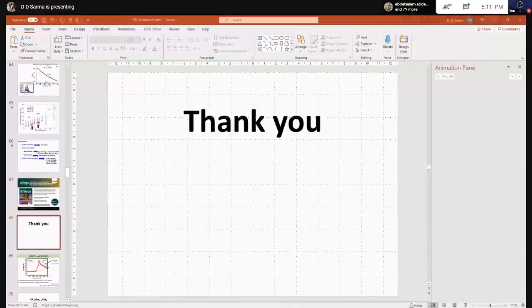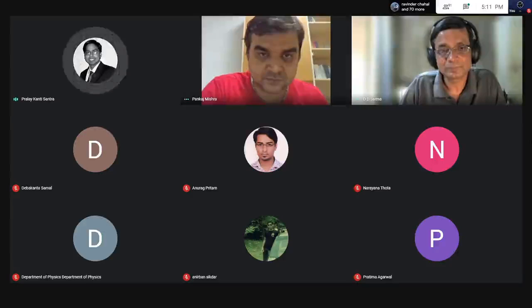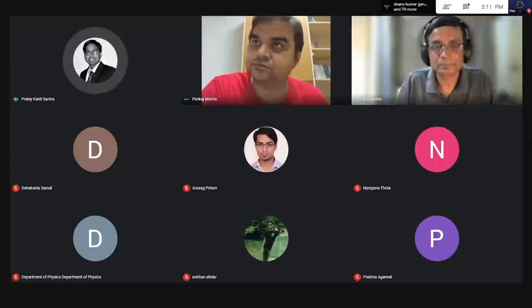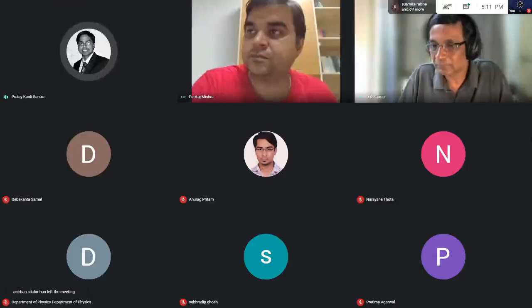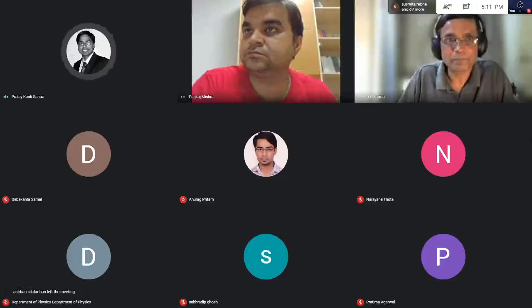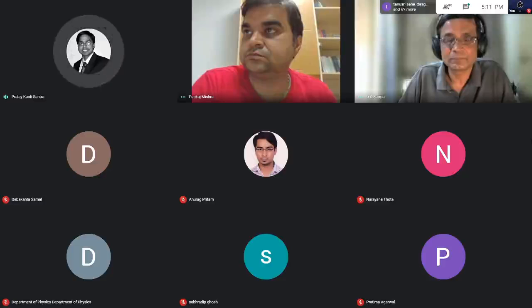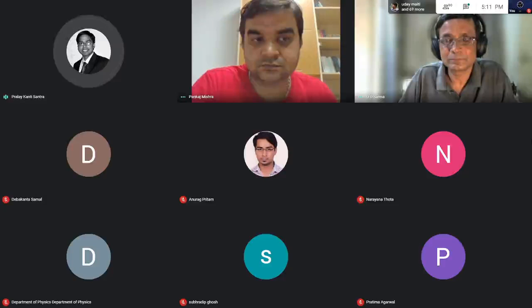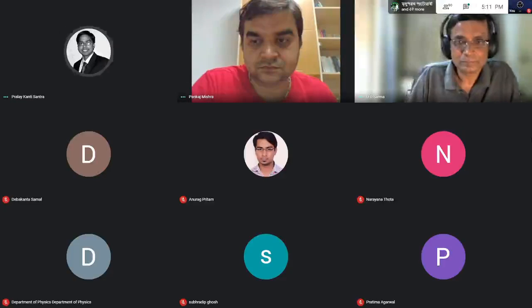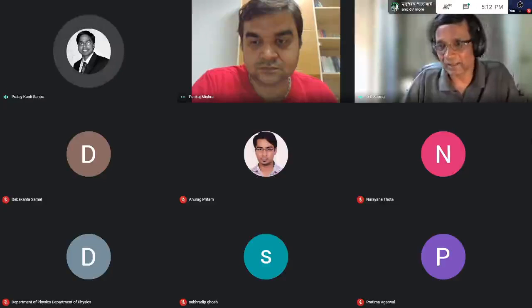So there is a question from Pralay Kanti Santra. If he's here, he can ask the question directly. Pralay? Okay. So he's asking, did you mention that the space charge region for a PN junction can extend up to several hundreds of nanometers, whereas in the case of ferroelectrics, it's only up to maximum 100 nanometers. So typically, what happens then, if the absorption coefficient is not very high, then the ferroelectric photovoltaics is not going to be helpful. Do you have any comment on how ferroelectric photovoltaics?